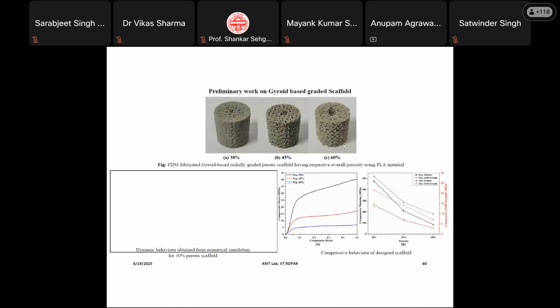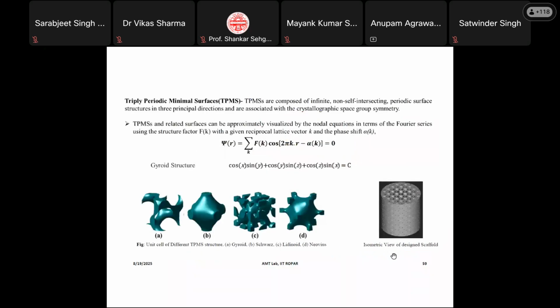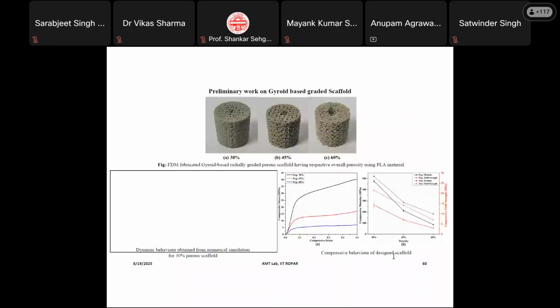We performed some tests of compressive behavior, and we found that these perform decently well for scaffold-based applications. And since they have this porosity, if they are made from the correct biomaterial, they will also allow for bioactivity. There are different images and other things of that.